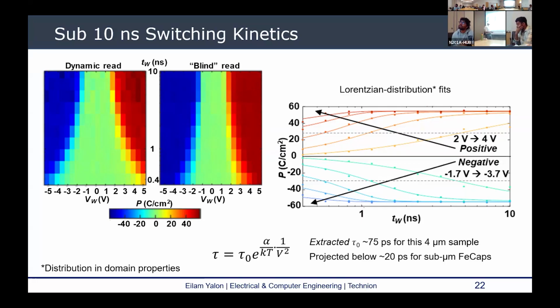And for the 4 micron sample, we can extract the minimum switching time at very high voltages. That would be about 75 picoseconds for these 4 micron capacitors. So if we scale capacitors below a micron, we expect the minimal switching time to be on the order of 10, or maybe below 20 picoseconds. And of course, the challenge with small capacitors would be to be able to probe the current, something that we are working on next.